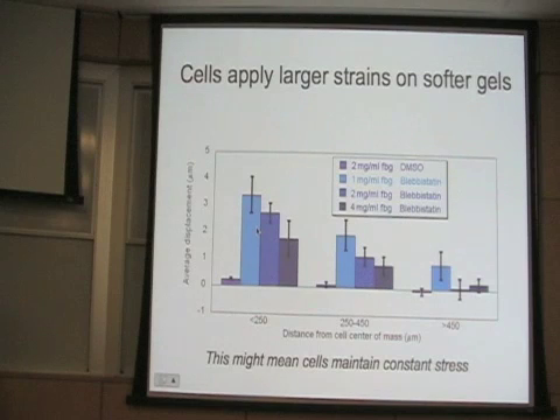And this may be relevant to whether cells are controlling stress or strain. The softer we make the matrix, that is, the lower the fibrinogen concentration, or let's look at it the other way. The larger the fibrinogen concentration and the bigger the stiffness, the smaller the magnitude of the displacement is. But again, we can see relatively good displacements 400, 500 microns away from the cell, especially when the gels are soft.